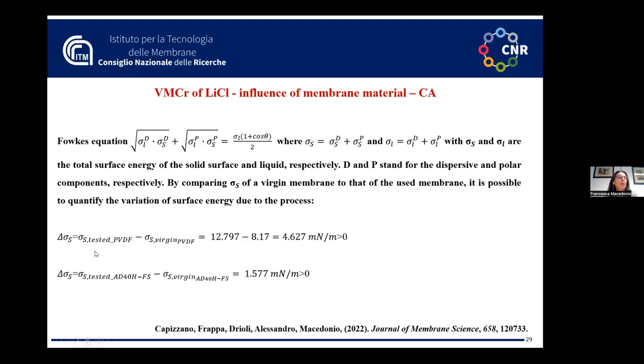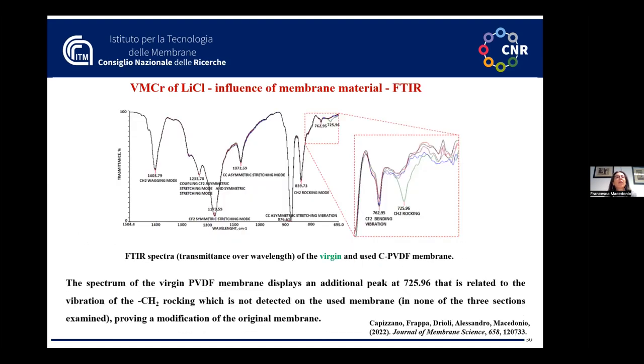As we can see, the measurement of the surface energy on the tested membrane and its comparison with the virgin membrane prove an increase of the surface energy. Therefore, there is a real reduction of the contact angle and of the hydrophobicity of the membrane. And finally, through FTIR and Raman analysis, we were able to prove the modification of the surface of the membrane that causes the unsuccessful lithium chloride crystallization via this membrane.